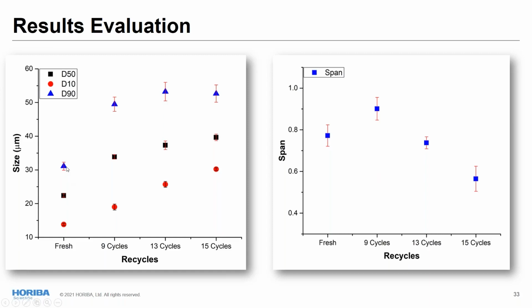The D90 has a very steep increase from the fresh to 9 cycles and gets stable afterwards, but not the D10. The D10 is almost a linear increment in size. Which means that if one of the sizes changes and another doesn't, we can see that very clearly in the span. So we have a span of almost 0.8, and then it actually increased a little bit and decreased drastically. This decrease means you're narrowing your particle size distribution, meaning most of the particles are getting closer in size, which is not necessarily a good thing.